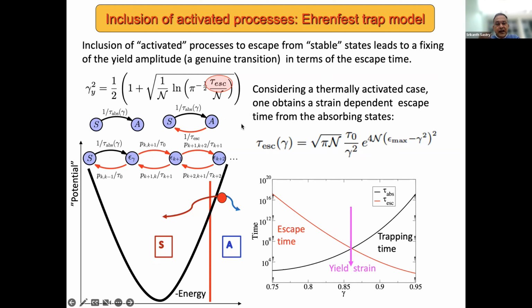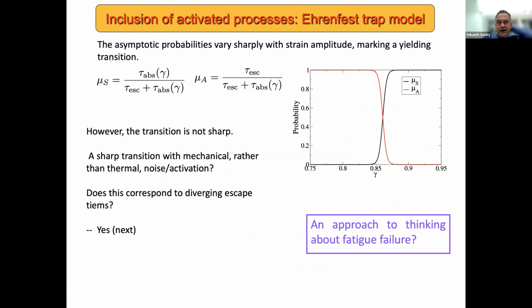So one can then calculate an escape time, which is a strong function of the yield amplitude. Interestingly, the trapping time, as I told you already, is a strongly increasing function of the strain amplitude. The escape time is a strongly decreasing function of the strain amplitude. The crossing of these two effectively gives you the yield points. But it also, as I've shown here, if I ask what is the probability asymptotically of being in the absorbing or the yielded state, they are very, very strong functions of the strain amplitude, but it's not a perfectly sharp transition.